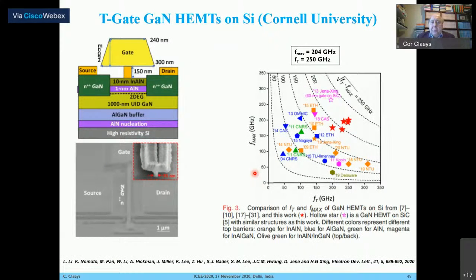Quite recently, there was a report from Cornell University on the T-gate gallium nitride HEMT device on silicon. And I've included this view graph only to point out that if you look at the frequency performance, that means the oscillating frequency versus the cutoff frequency for different devices, here the red data are for the T-gate gallium nitride HEMTs, and you see that they were able to achieve an Fmax of more than 200 gigahertz and an FT of 250 gigahertz. This is very good frequency performance for gallium nitride on silicon.